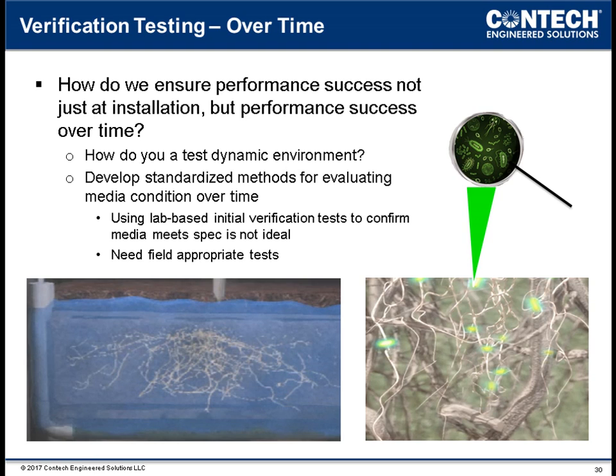Additionally, mulch degradation over time contributes organic fines to the media bed, replenishing the system's organics as they're consumed by microorganisms, especially if you're not actually replacing the mulch, but simply adding more mulch over time. We've collected media samples from high-flow bioretention systems of different ages and observed an increase in organic content over time. You might think, well, my flow rate's going to be reduced with this increase in organic content, and this certainly hasn't been something we've observed in studying older systems. This is likely due to processes benefiting hydraulic capacity that counteract this increase in organic content, like physical processes such as wetting and drying of the media that creates preferential flow paths over time.